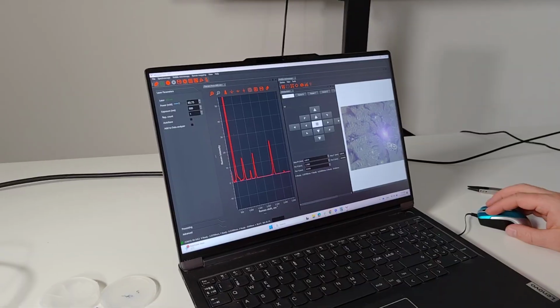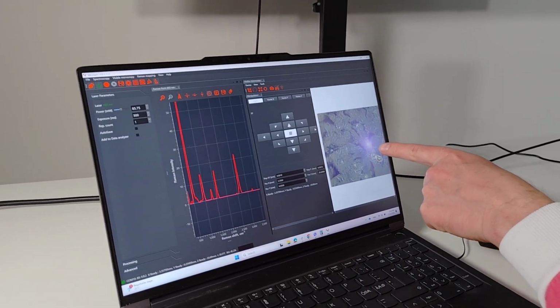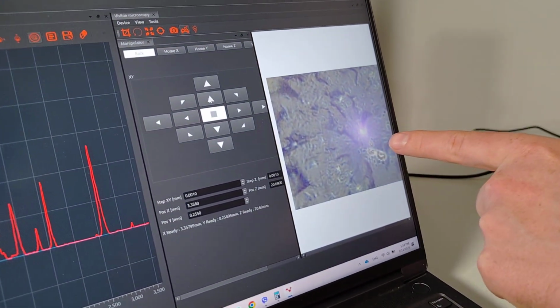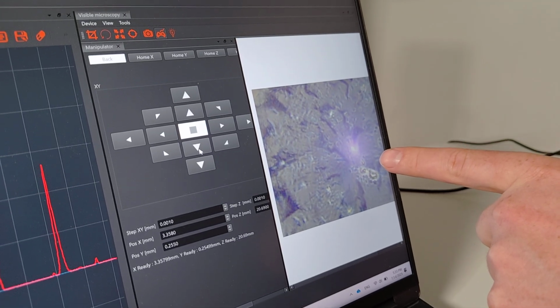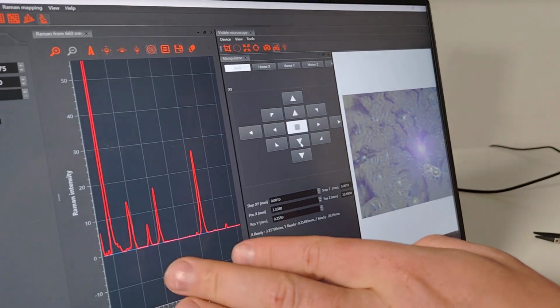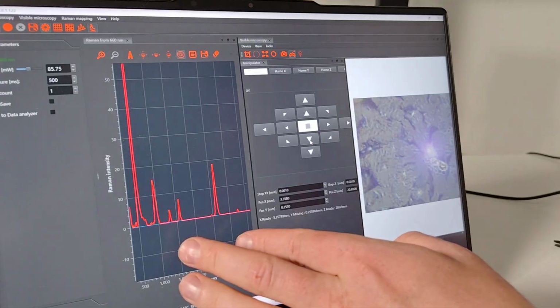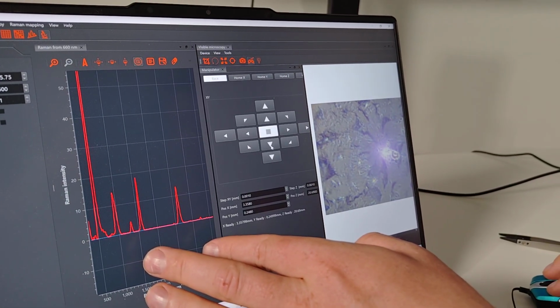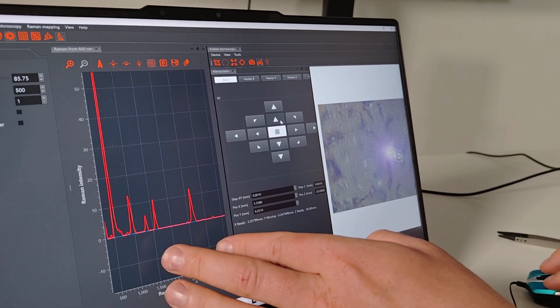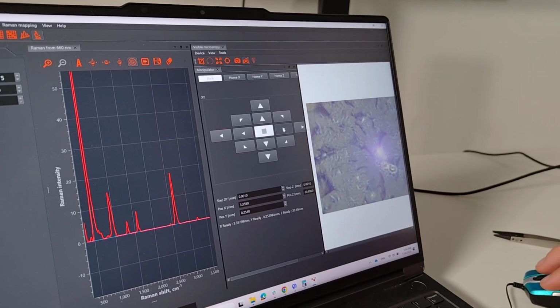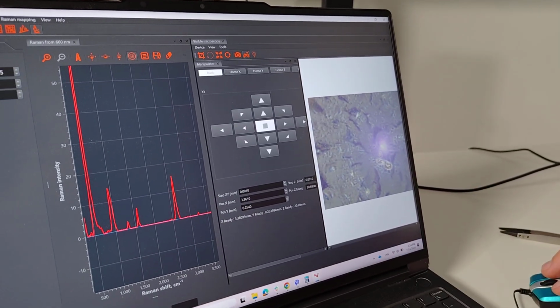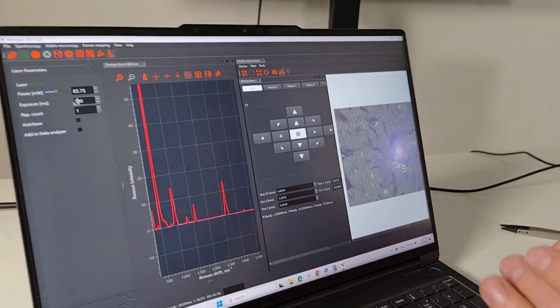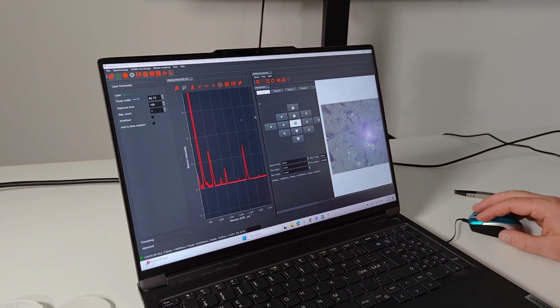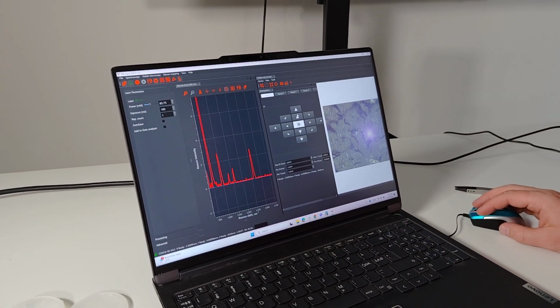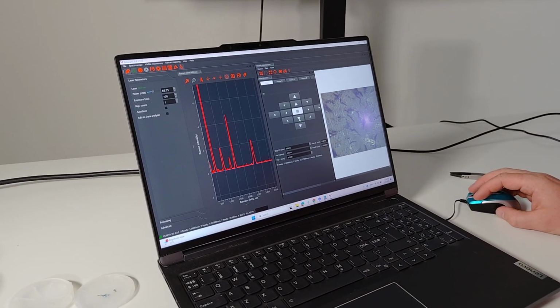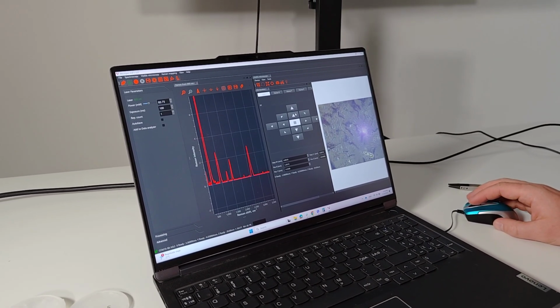We of course then can run Raman mapping. Oh, look, I found actually a very different spot with a different graphene composition here. You can see by the peak ratio. So if I move slightly, the peak ratio is different. And I can go back to the same location. This way we can do graphene mapping in very fast mode. So basically 100 milliseconds is not a problem at all for such measurements. You can see that it's a very fast and convenient way of doing that.